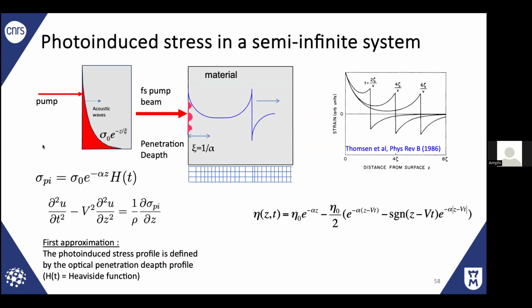If you remember, if you shine light on a solid, you emit such a bipolar pulse. So there is a tensile one and a compressive one. This is exactly what we measure. So with X-ray, we can reconstruct the profile of the light-induced strain in that solid.